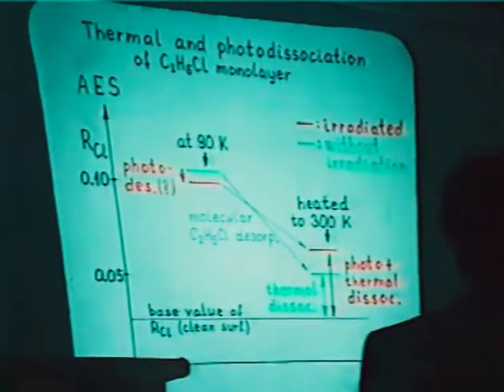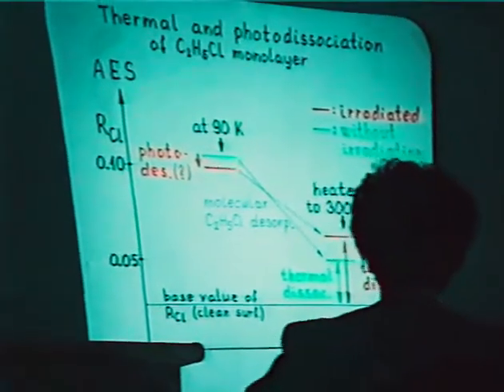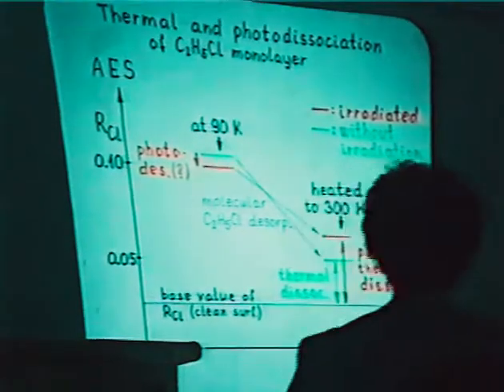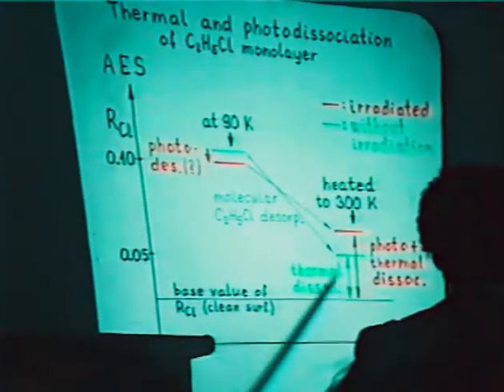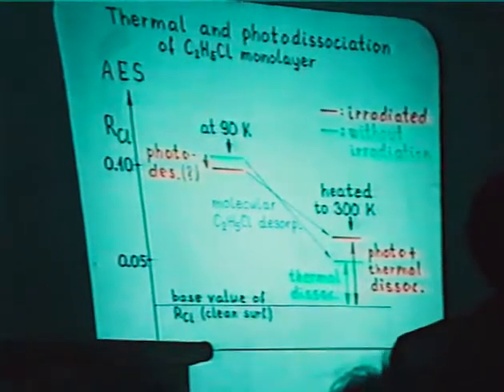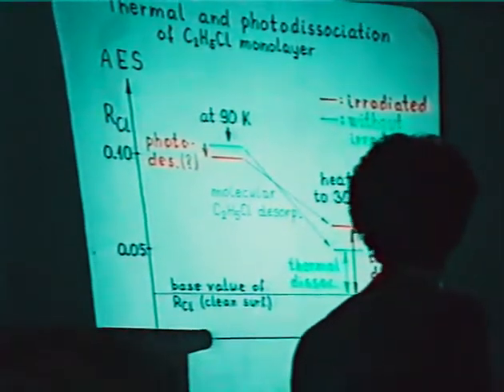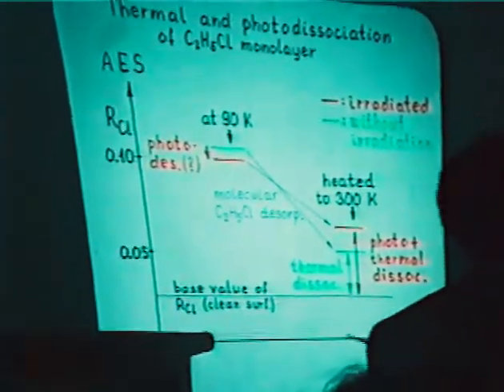We made Auger measurements as well. The thermal and photodissociation of ethyl chloride was followed by the chlorine Auger intensity. When a monolayer of ethyl chloride was adsorbed at liquid nitrogen temperature, and the sample was heated to 300 K, ethyl chloride dissociated. It is not the effect of the electron beam because every point represents distinct measurements.